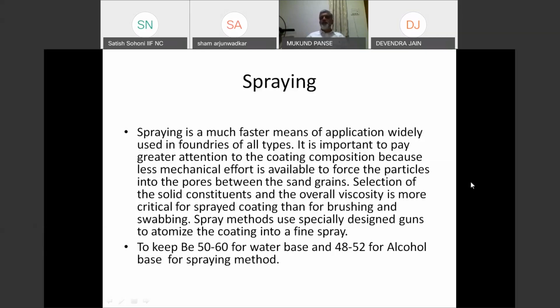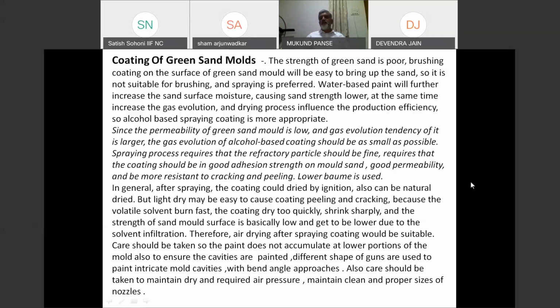The viscosity used for spray coating is slightly lower than for brushing. For water, it is around 50-60 and slightly lower for alcohol base. Again, spraying is problematic where intricate shapes are there. You have to use different angle spray guns for coating those portions, or you may have to brush those areas. Again, the nozzle size through which your paint is being sprayed should be checked intermittently so you get proper thickness